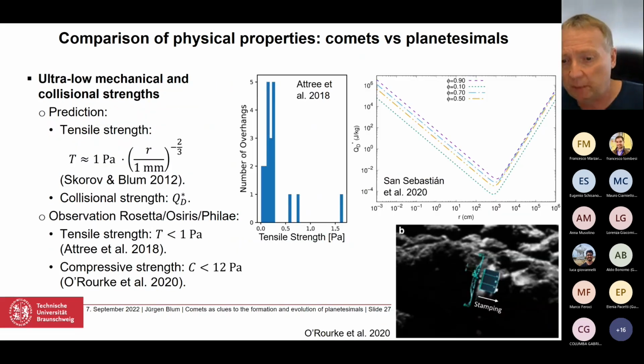Strength. Strength is an extremely important measurement at Comet 67P, Churyumov-Gerasimenko. Yuri Skorov and I, back in 2012, so 10 years ago, had already predicted what the tensile strength of a pebble pile would be. And the tensile strength T here is on the order of 1 Pascal if the radius of the pebble is a millimeter, and if the radius is larger than a millimeter, it scales with a power of -2/3. So for a few centimeter pebbles, this tensile strength might be as small as 1/10 of a Pascal, which is extremely important for understanding comet activity. But that's another theme, not for today.